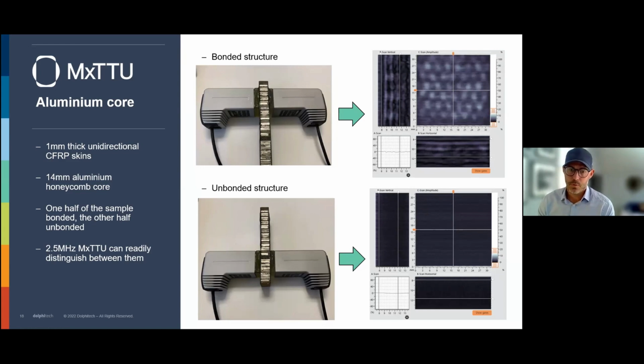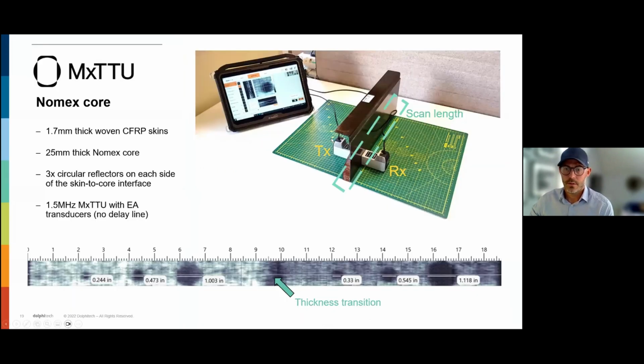So here you see an example of a honeycomb structure that is composite honeycomb, and you can see when the bonding has released on either side of this sandwich structure. If you look at the further one where we have stitched together an image, this is actually inserts put into a honeycomb structure, and you can see these black areas where there is no adhesion between the honeycomb and the carbon fiber. So very powerful tool where you cannot use simple pulse echo.